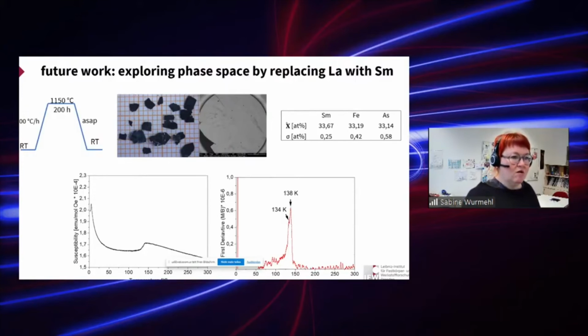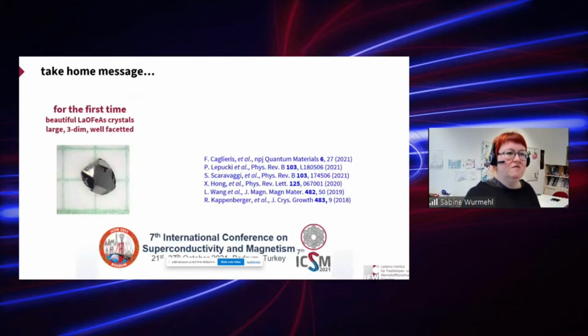And as you can also see here, we see the transition of the structural and the spin density wave phase in the magnetic data, which are very well in good agreement with what has been reported for the samarium 1111 phases. And of course, here we will also play with cobalt doping substitution series. Also, we want to study the interplay of the iron magnetism with the samarium magnetism. And this is what will keep us busy for the next month.